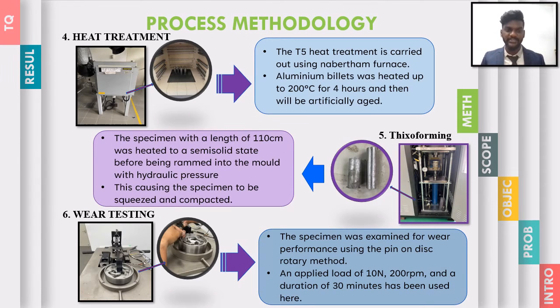The heat treatment is the fourth step, and the heat treatment was done in terms of T5 heat treatment using a Nabertherm furnace that is available in the FKP laboratory, at 200 degrees Celsius for up to 4 hours for each specimen, and the specimen was also artificially aged for approximately 3 hours after the heating was done, and the specimen was collected later.